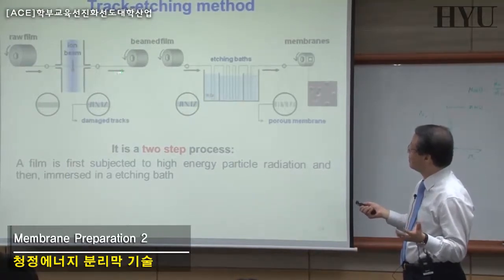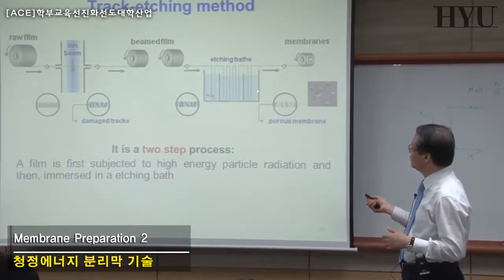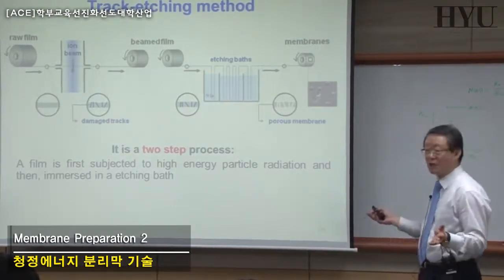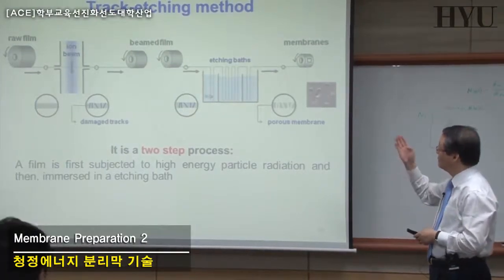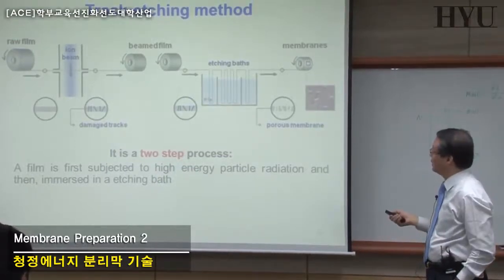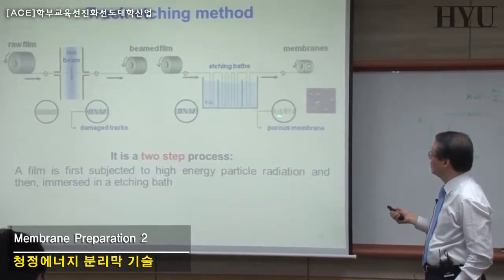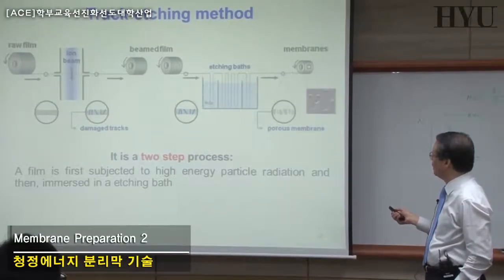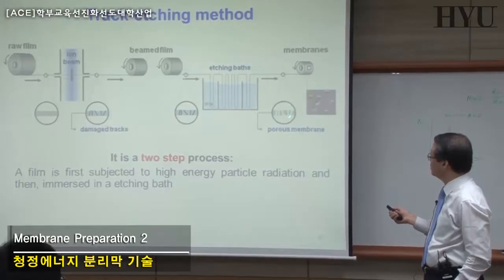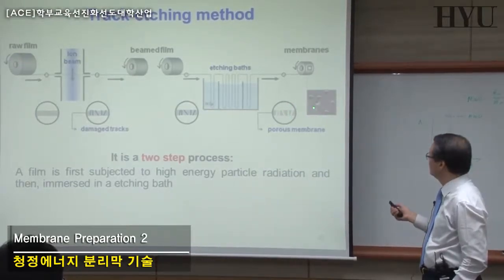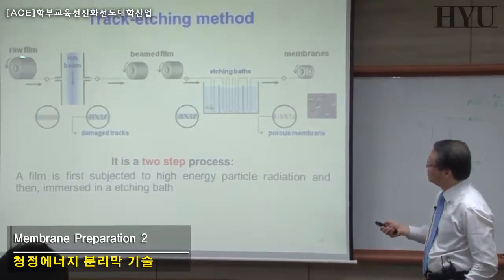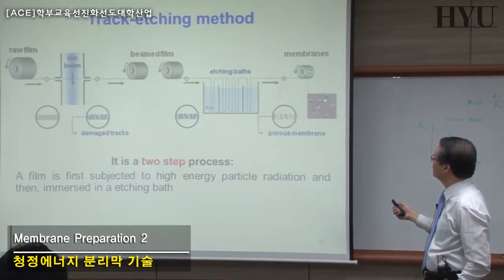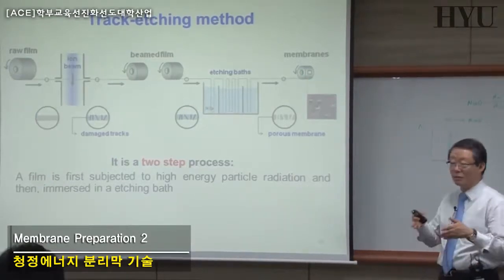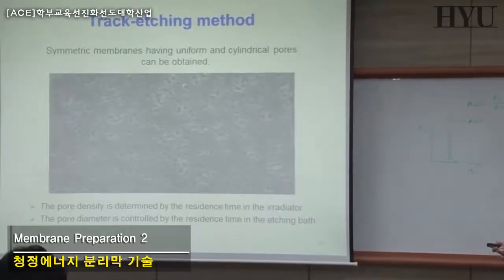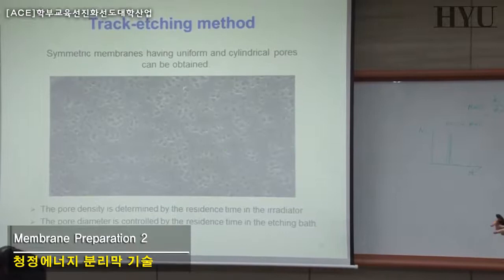after this bombardment. But if I put this film into the etching solution, such as sodium hydroxide or a very harsh solution, then you can etch the exposed area, so that the blue colored area will be gone, making a porous structure of your membrane. So you can see this porous structure, starting from a very dense film. After these two processes, we have a polymer that is etched and has holes. It looks like drilled membranes. Now, this is quite messy.